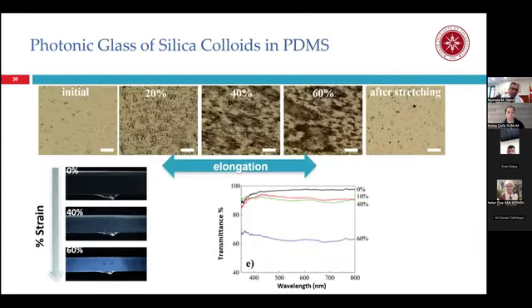So in the optical microscopy image, you see initially the image of the original composite material. You apply elongation of 20%, 40, 60. You see extension of the colloidal systems in the uniaxial direction. Then after stretching and releasing, you return back to more or less the same condition. I don't know whether you can see on your screen, but in 40 and 60% extension, you see slightly green and slightly blue colorimetric change. In transmission spectra, you see the original one, the black one. If you apply extension, same material, at 60% extension, you see there is already opaque material, okay?